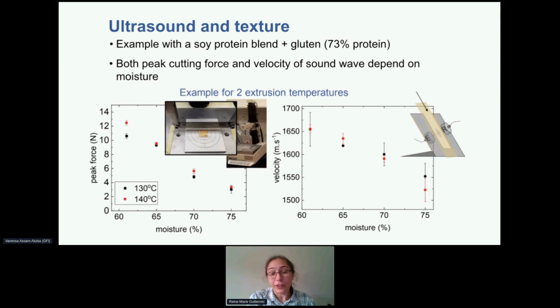The velocity changes the same way. So it's also decreasing with moisture. So basically, when you increase the moisture content, you will have a lower velocity. I put here two different temperatures of the barrel when we extrude at different temperatures. One is 130, the other 140 degrees. And so it works for both. So you can go forward.